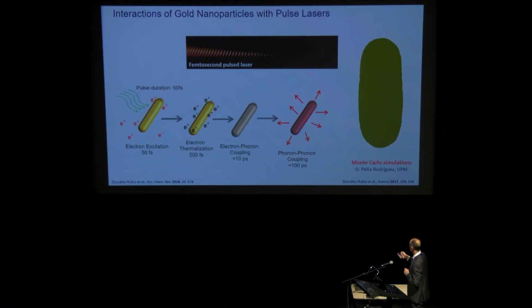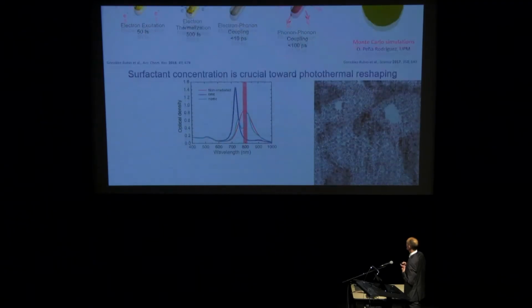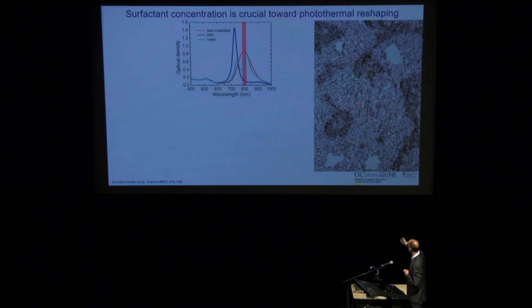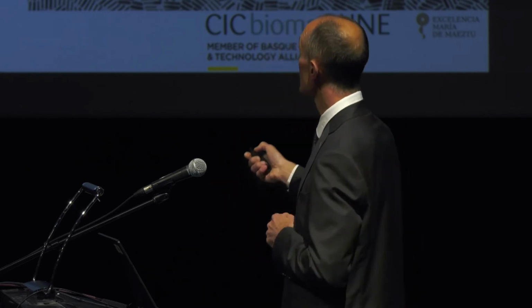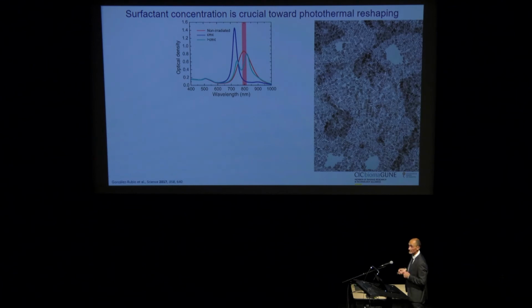When the wavelength of the light is not matching the aspect ratio of the particle anymore, this reshaping will stop. And as a result, you can go from dispersions like this, with a spectrum like the red one, into spectra like the blue one, which is as narrow as the theoretical prediction. However, this only works if you have the right concentration of surfactant.